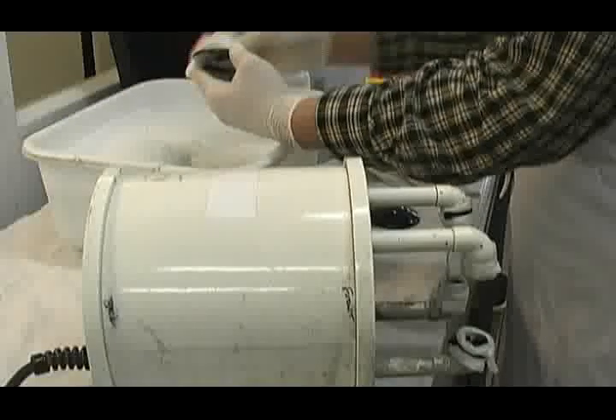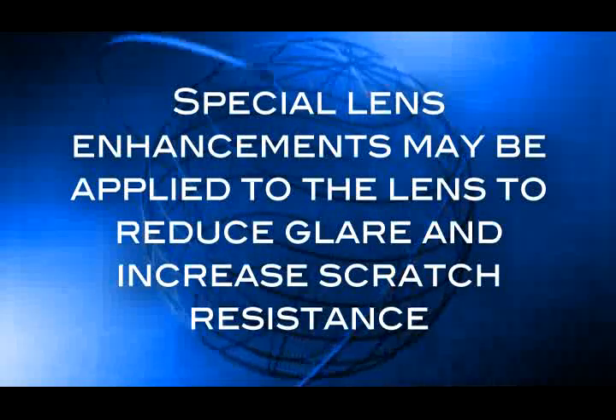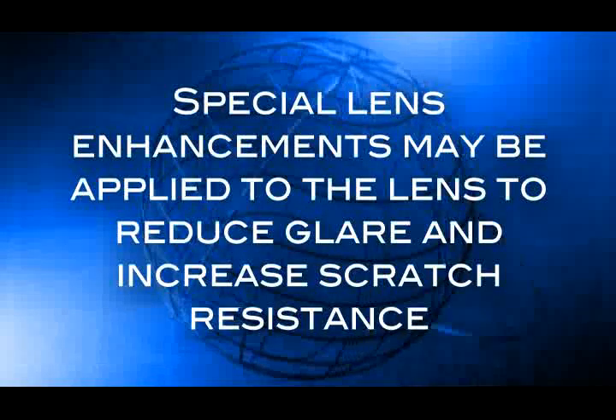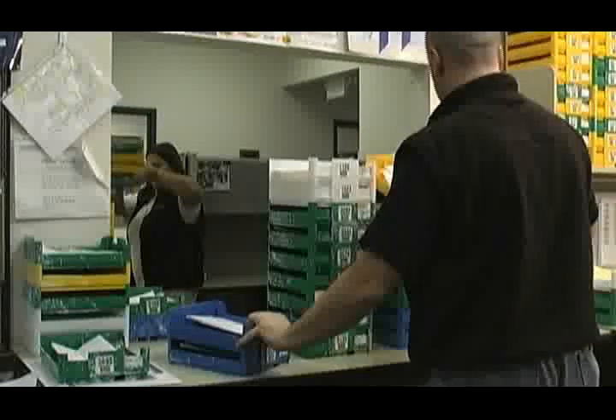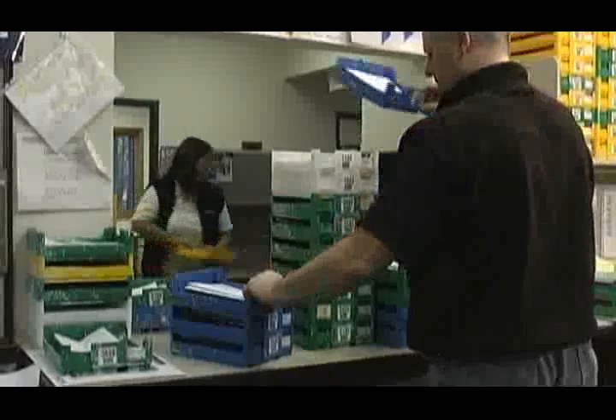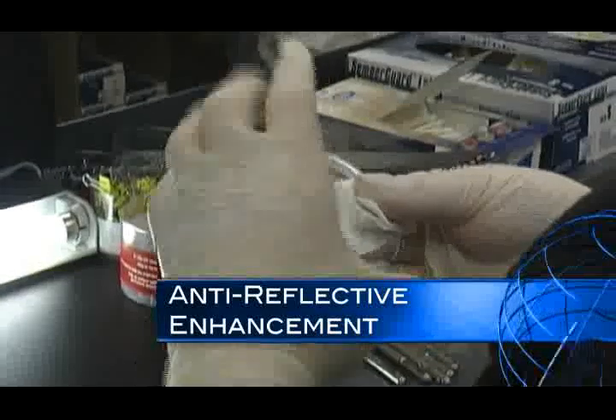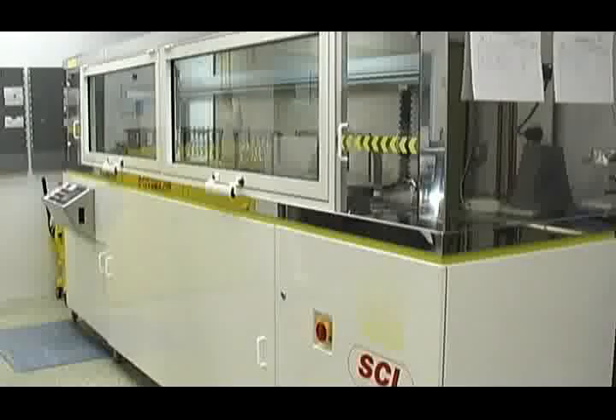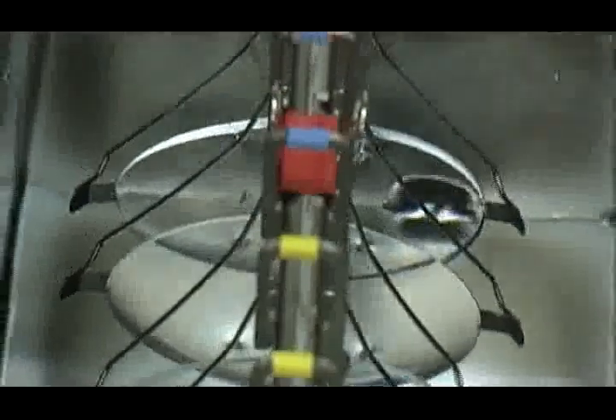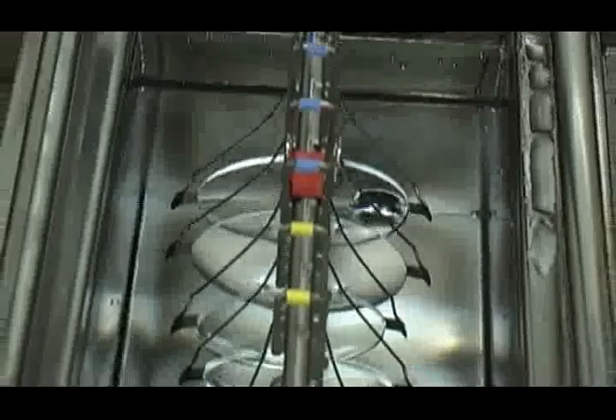The lens block is then removed and the lens is washed and inspected. At this point, special lens enhancements such as a premium anti-reflective coating may be applied to the lens to reduce glare and increase scratch resistance. Different lens materials require different anti-reflective lens treatment chemicals. For this reason, the laboratory begins by sorting the lenses into batches of the same lens material. Once sorted, the lenses are once again washed by hand and manually inspected to assure there are no flaws. Flawless lenses are placed into a special machine that ultrasonically cleans the lenses and then etches them. Much like scraping or roughing up paint on a house before repainting, the lens etching process assures adhesion of the treatments to follow.